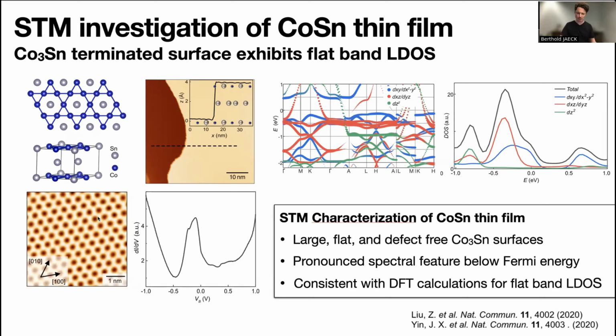When we now do spectroscopy on the surface, we detect a relatively sharp peak structure just below Fermi level. And now, for those who perhaps have been studying twisted bilayer graphene and other materials that have a flat band, we all know that this is kind of the telltale sign, sort of the minimum requirement to, I guess, study flat band physics, right? I think this is even much broader than perhaps what most people see, or what even myself I've seen in twisted bilayer graphene.